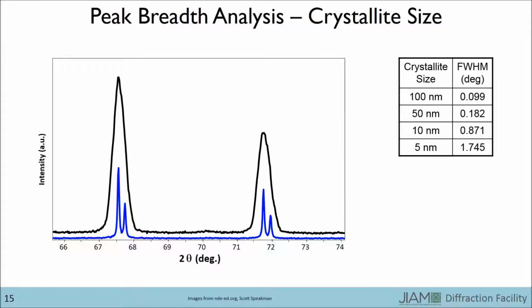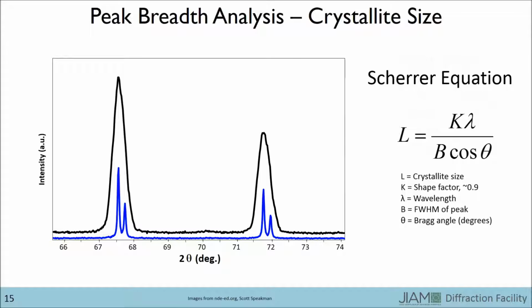Typically, we like samples with a crystallite size of a few microns. However, we can certainly accommodate crystallite sizes on the nanometer scale as long as you don't mind the peaks looking very broad. In order to calculate the crystallite size, a popular method is to utilize Scherrer's equation, shown here. It is a pretty straightforward equation where the crystallite size equals the shape factor, typically taken to be around 0.9, times the wavelength of the X-rays divided by the product of the full width half maximum in radians of a particular peak and the cosine of the Bragg angle of the same peak.